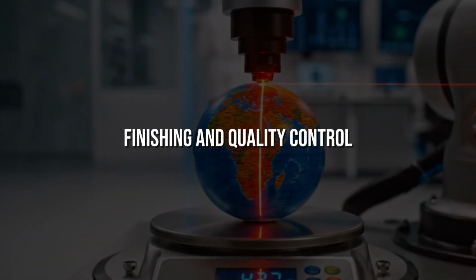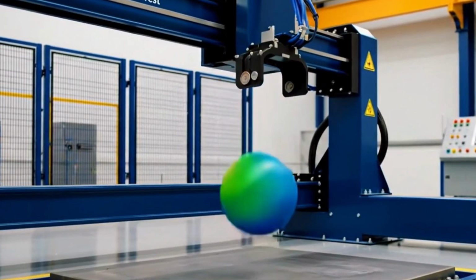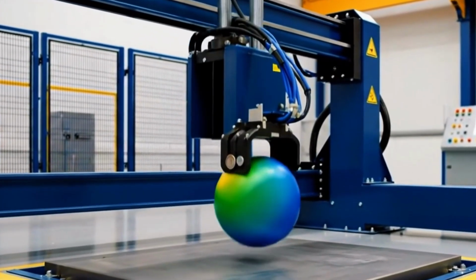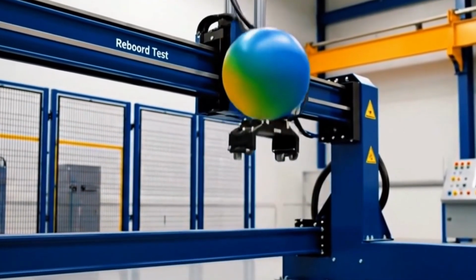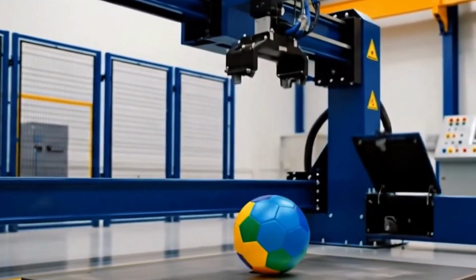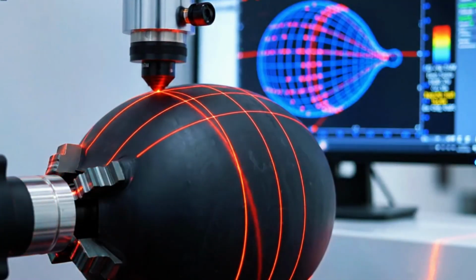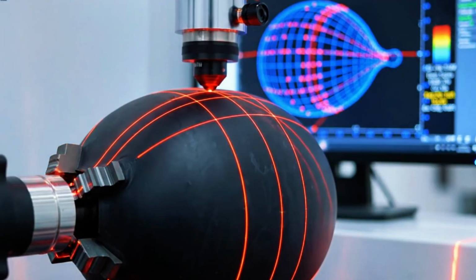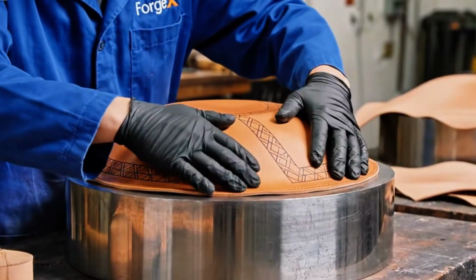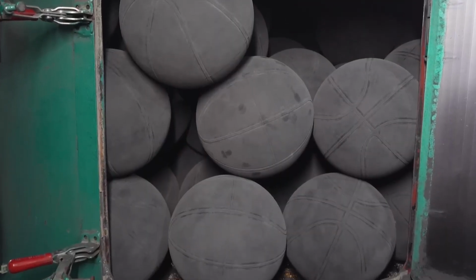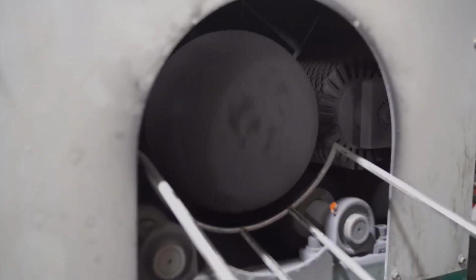Finishing and quality control. After molding, rubber balls undergo deflashing, the removal of excess material that forms along mold seam lines. This can be done manually, through tumbling with abrasive media, or via cryogenic deflashing, where balls are frozen with liquid nitrogen and the brittle flash is removed through mechanical action.